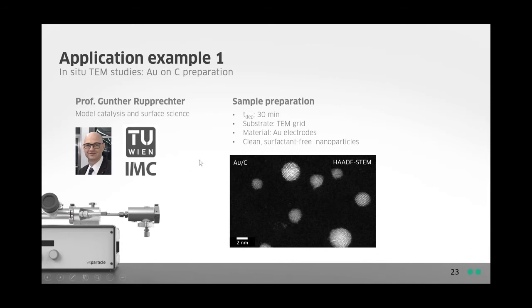After 30 minutes of deposition using gold electrodes in our VSP G1 nanoparticle generator, we're able to deposit gold nanoparticles on a TEM grid in the diffusion accessory, and we were able to obtain clean, surfactant-free nanoparticles. What you can see here from the HAADF STEM image are really small crystalline gold nanoparticles that were deposited easily on these TEM grids.